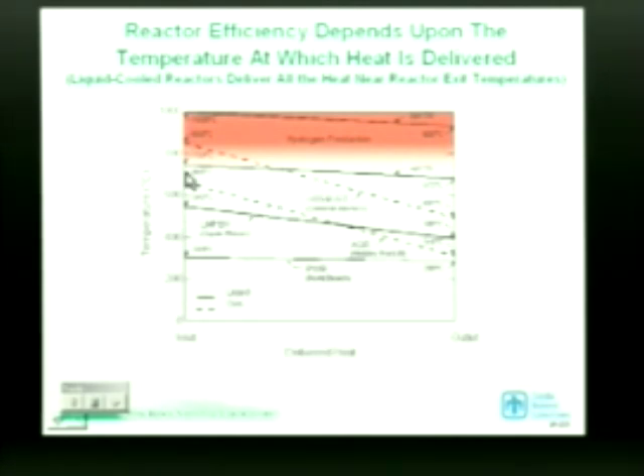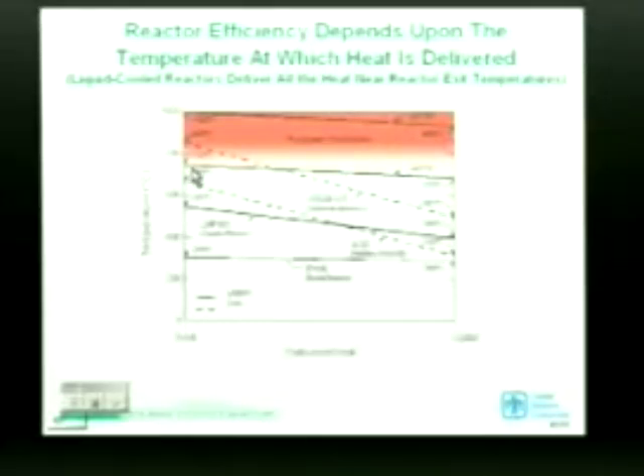Now let's take our advanced high-temperature reactor with a liquid coolant, and that's the important thing. It happens to be a molten salt, but the really important thing is it's a liquid coolant, and it's operating with an exit temperature of 750 degrees C. But the pumping horsepower is low, so we can deliver most of the heat at high temperature. Now, isn't that interesting? The average heat delivered from a molten salt cooled reactor will be higher than from an HTGR, even though the exit temperature from the reactor is 100 degrees C less.